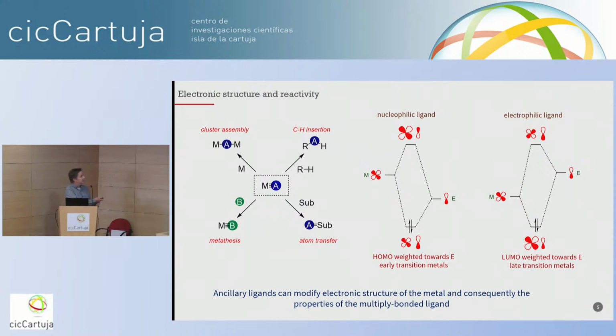Okay, so what's been shown for metal ligand bonds, and specifically these atomic ligands, what kind of reactions could you do? Just for some hypothetical atomic ligand, you could do a CH insertion, like I showed you for the iron(IV) oxos, to functionalize hydrocarbons. You can do atom transfer to different substrates, so you oxidize the substrate. Another reaction that is often seen is metathesis, so exchanging one atomic ligand for another ligand. And then you could also use these as precursors for making clusters in a well-defined or controllable fashion. So there are many things that you could do with these.